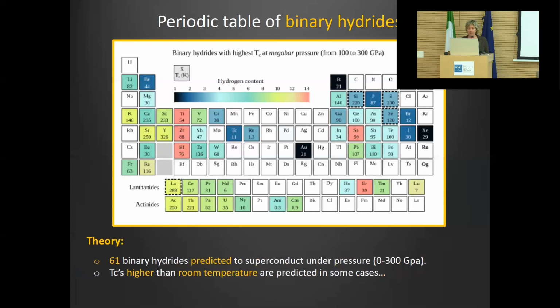Okay. And this is our periodic table of binary hydrides. As you see, it's a standard periodic table. And there are the elements, and a few of these elements are colored, and the elements which are colored are those that form a binary hydride which has some critical temperature in a range between 100 and 300 GPa. You see also a number below the name of the element. This number gives the highest critical temperature. And you see also a color. And the reason why you have all these colors in this table is that at these pressures, there are many, many different hydrides that can form for a single element.